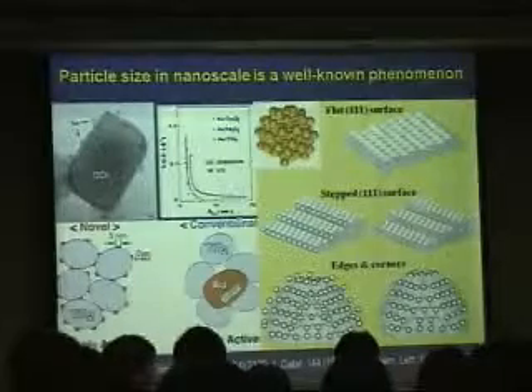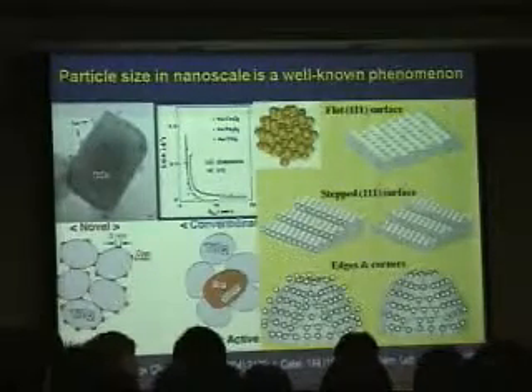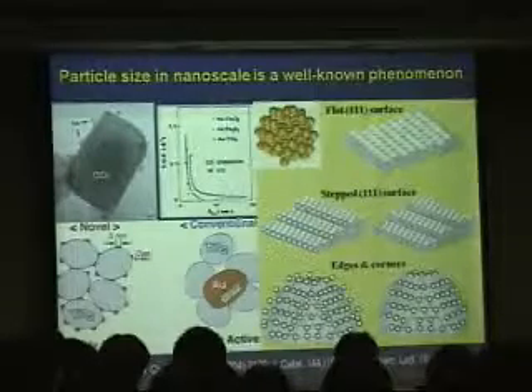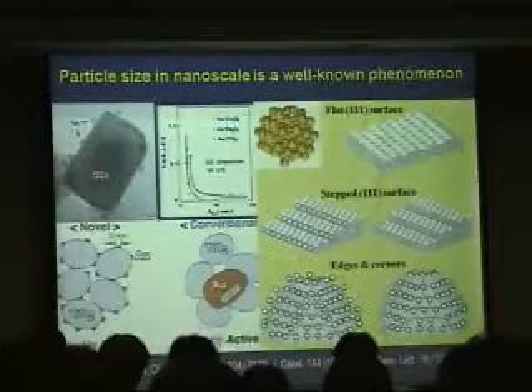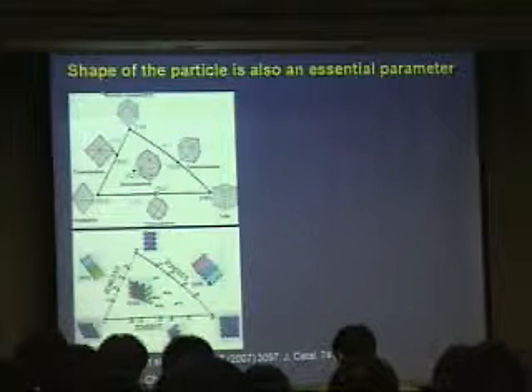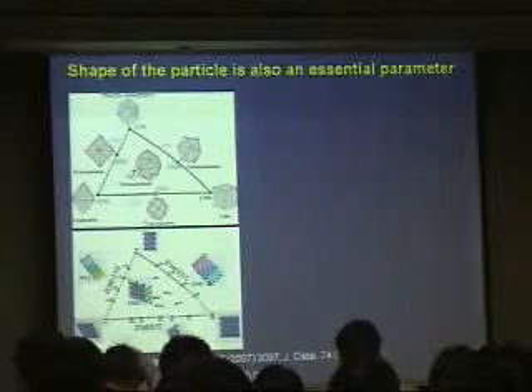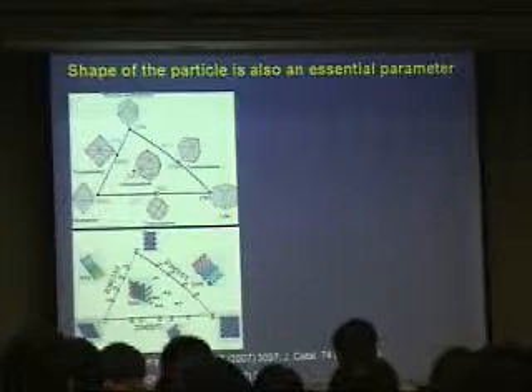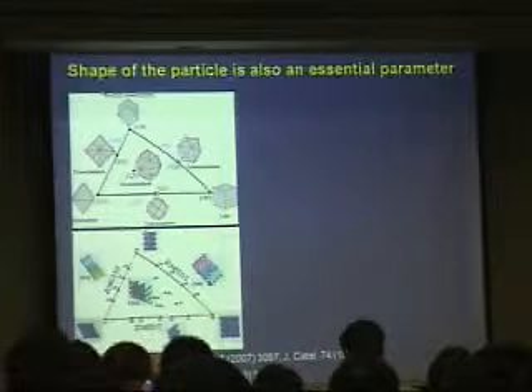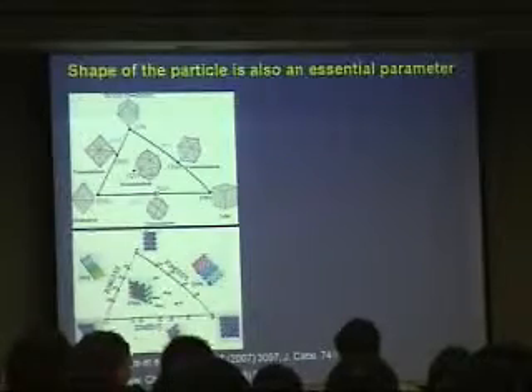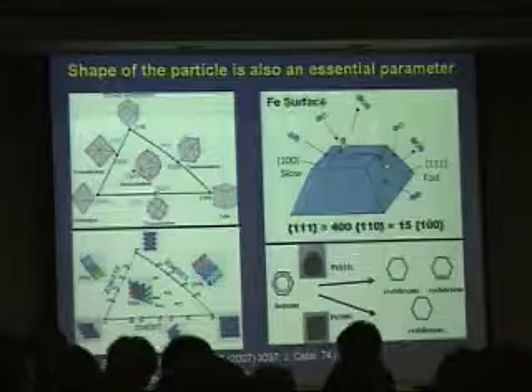On the other hand, if we make the surface of the catalytic particle expose those low coordinated atoms, that means we could greatly increase the density of active sites on the surface. That's why some people analyzed the possibility of changing the shape of these particles. By changing the shape, they can expose different crystal facets. On those facets, the coordination number of the atoms can be adjusted. If we can make them more or less coordinated, we can make them more active for the reaction process. Actually, this has already been confirmed by some surface chemistry.